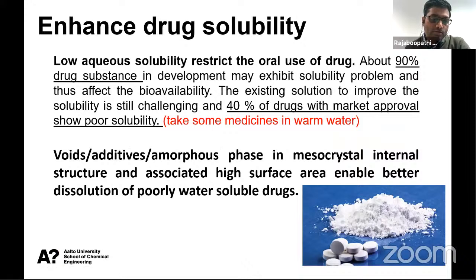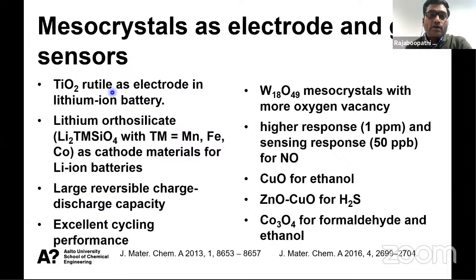We can also use titanium as an electrode in lithium-ion battery. Lithium orthosilicate has been used as cathode in lithium-ion battery. And if you use an electrode in the form of mesocrystals, the lifetime of the battery is very high. For example, excellent cycling performance, large reversible charge discharge capacity has enhanced when you use the electrode in the form of mesocrystals.